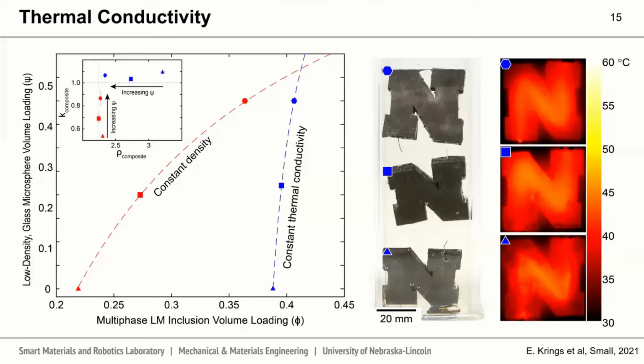The image on the right shows each of these materials pulled out of the liquid and then used as a thermal heat spreader, where there's a resistive heater embedded within each of these, and we see a very similar thermal response to this applied heat load. This verifies that we're able to independently tune the thermal conductivity and density of these composites by introducing a new phase into the liquid metal.